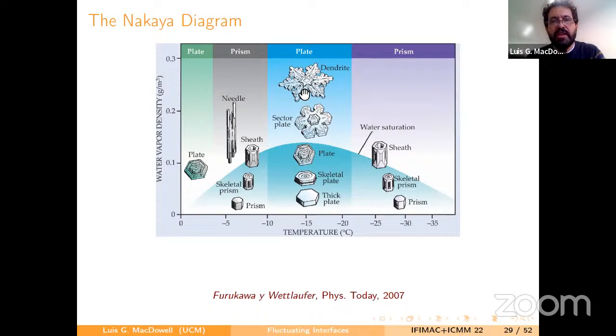Okay, so we're all familiar with dendrite-like snowflakes, which appear in postcards, in Christmas cards. But actually, when humidity is small, the crystals grow in a much simpler shape. They always adopt a hexagonal prism shape. But the interesting thing is that the shape of these hexagonal prisms will change with temperature. If you are close to the melting temperature, the prisms will grow as plates. If you go down to -6 degrees, they grow like columns. If you further cool the system, they grow again like plates. And with further cooling below -25 or so, you get columns again.